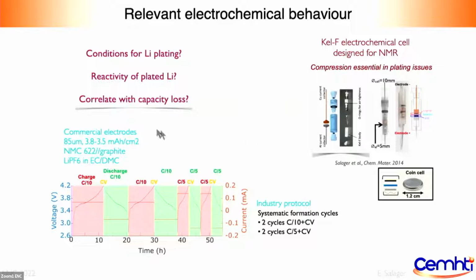And so we use commercial electrodes and protocols from our partners. So initially, this is what you have to describe the electrochemistry. In blue is the voltage curve, charge, holding the voltage at 4.2 volts, and then discharge. In red, this is the current, and this tells you how fast you charge. So we always prepare our batteries in the same way, and we check that they do give what you expect.